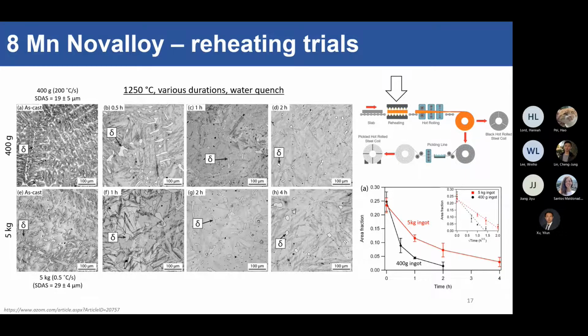Delta ferrite in your steel actually kills the hot ductility. So if you try to roll something like this, it will immediately break up. It's bad. So we want to homogenize it and see if the delta ferrite actually goes away. At different times here, you can see that the delta ferrite first globularizes up together, like Terminator, and then after that, they slowly go away.